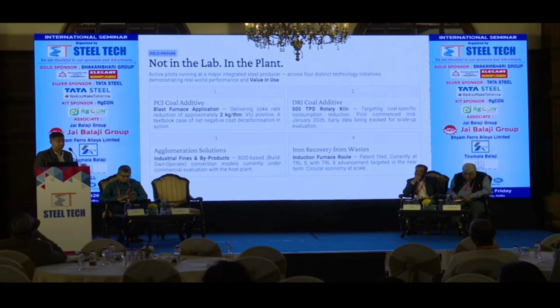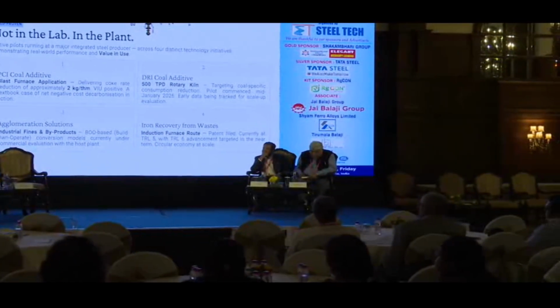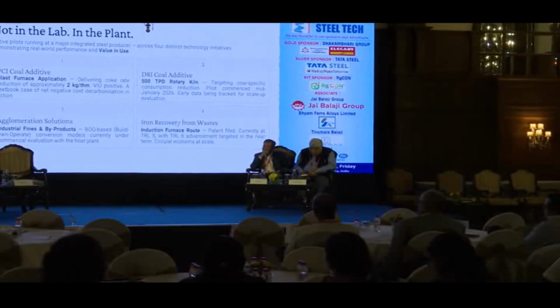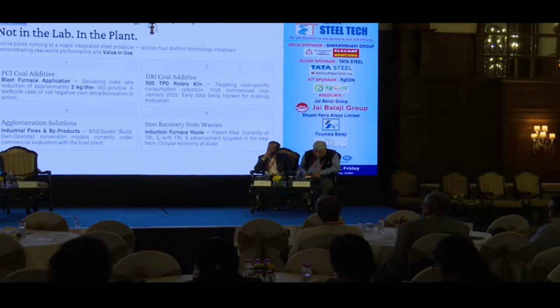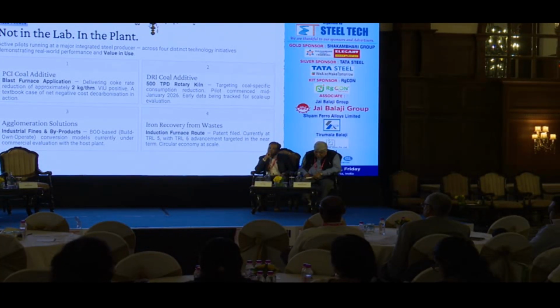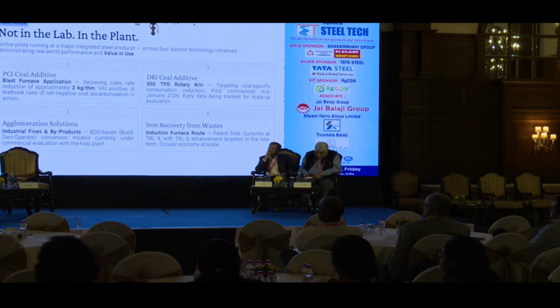Iron recovery from waste. Now this is very interesting. We heard in the previous presentation regarding the potential of hydrogen, the potential of directly reducing, getting value deriving metal from the ores. So we have filed a patent which basically specializes in recovery of iron from iron rich wastes like mill scale, red mud and iron ore slimes in an induction furnace atmosphere. So induction furnace is normally a pure melting furnace. There is no smelting reaction which is happening. So that is where the technology is.